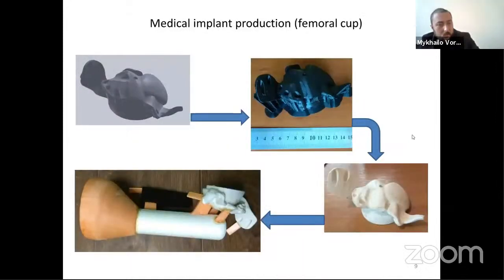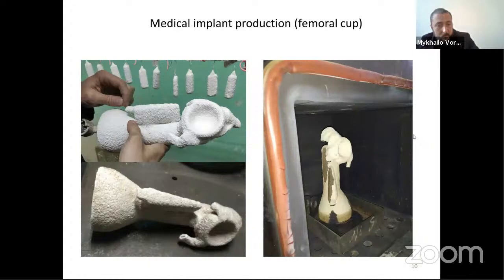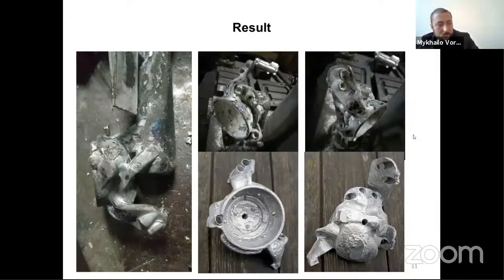The next step was to produce a real implant. The first step was to create a model. We chose PLA plastic because of its mechanical properties and ability to be printed as a small detail. Then the PLA part was added to a polystyrene gating system and formed into ceramic mixture. After drying and sintering at 1100 degrees Celsius, the mold was ready to be cast with titanium. And here's the view of our mold. And here's the example of a detail. As you can see, it's almost perfect as for casting.